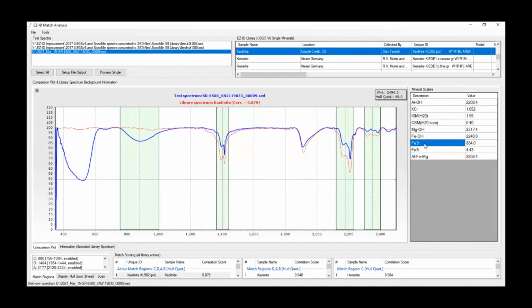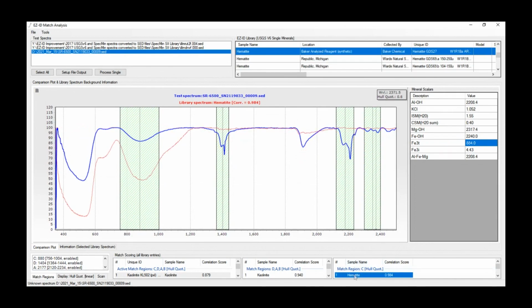So if I go over here to the Fe3+ scalar, this is a very important scalar for hydroxide type and oxide type Fe3s that you might be looking for. Hydroxide type Fe3 minerals typically have values greater than 900 nanometers, and oxide-type Fe3 minerals have values less than 900 nanometers. This scalar is used most commonly for hematite versus goethite. So if we look at our value, it's giving us a value of 884. So that's being less than 900 nanometers. I could look at this value and automatically know that this is hematite. And the EasyID software is matching that very well as well.